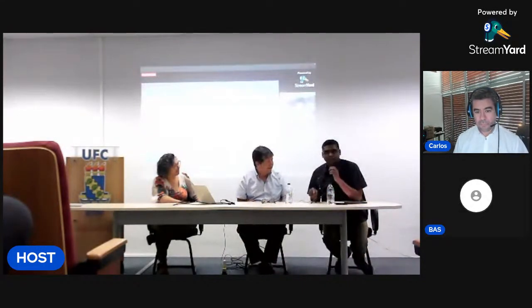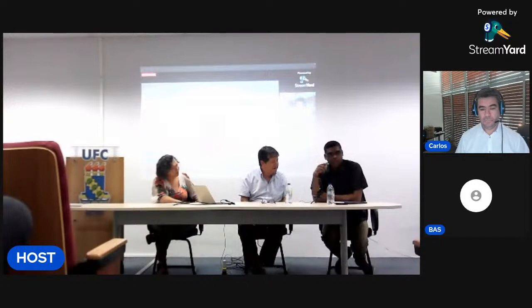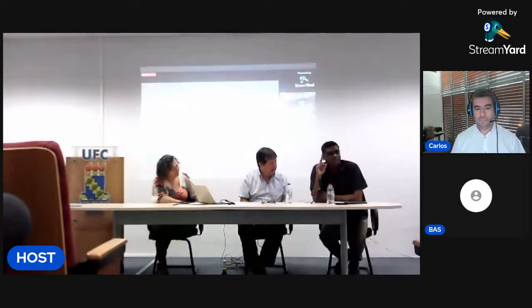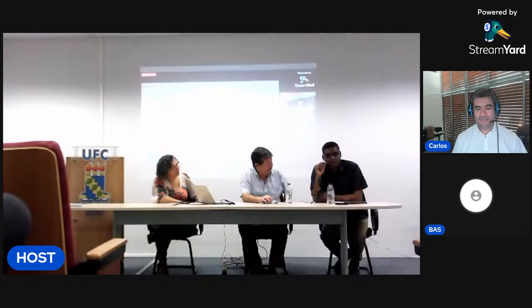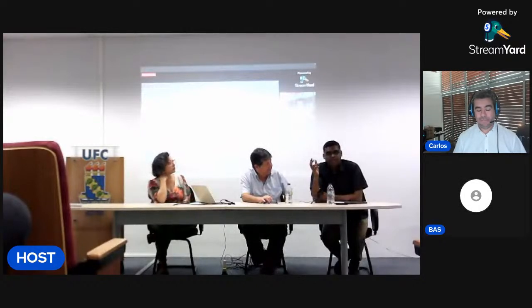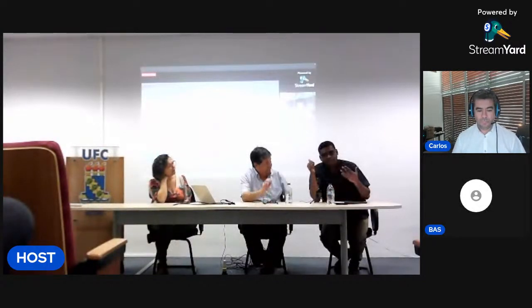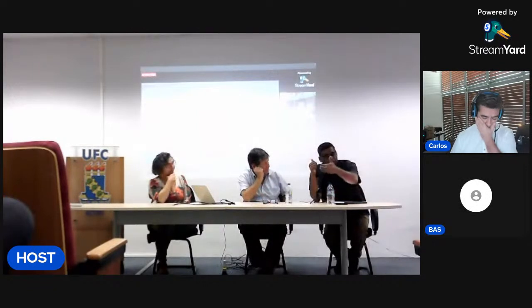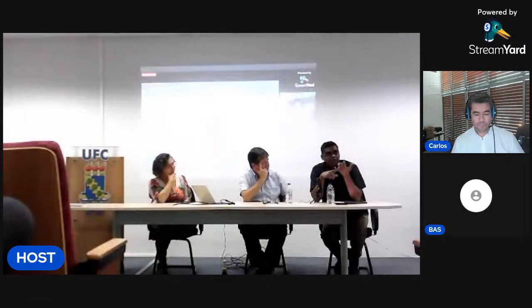Yeah, well, I agree. I think when it comes to CO2 capture specifically, as you mentioned, SOx and NOx are important, but I think we should also not forget oxygen, especially with amine-based adsorbents, which are probably the most advanced, at least for direct air capture. Oxidative stabilities are poor. There have been some really interesting materials that came out with very interesting isotherms, but from what I hear, when you put it in oxygen, it collapses essentially. So oxygen itself can be a big issue. So in such cases, there seems to be a preference towards physisorbents. Then, of course, water can be a disaster.